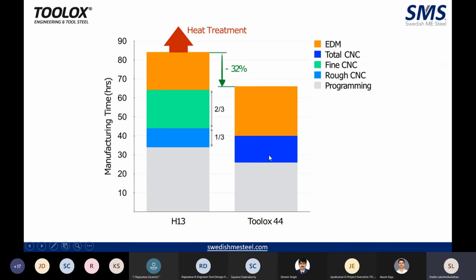And you can directly go for your fine CNC, where in H13 you have to go for rough and fine CNC. And Toolox 44 being a 45 HRC material, you will find the EDM time to be a little bit higher when compared to your annealed material, which is understandable. So taking everything into consideration, from raw material to the finished stage, the total manufacturing time is drastically reduced by around 25 to 30% when using Toolox 44 compared to your regular material.